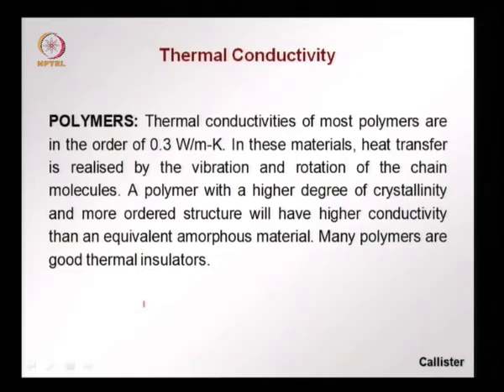A polymer with higher degree of crystallinity, that is a more ordered structure, more arranged structure, will have higher conductivity than an equivalent amorphous material which has a lot of space between the chains. In the case of higher degree of crystallinity, we have a better packing, and therefore the conductivity is better. Many polymers are also good thermal insulators, again because of the amorphous nature and the lack of packing.